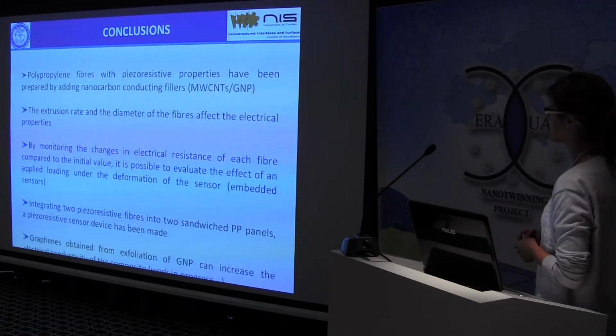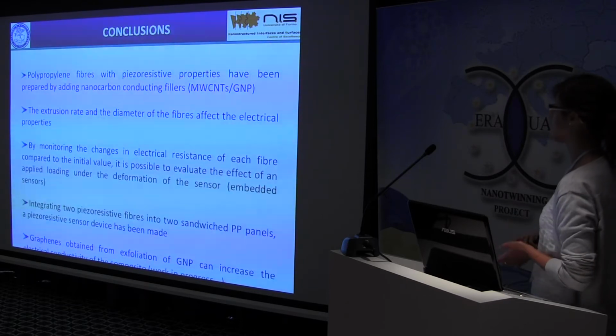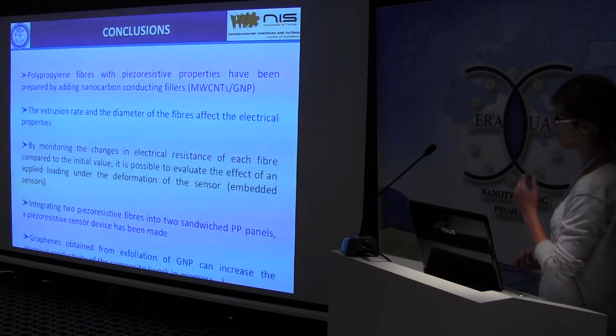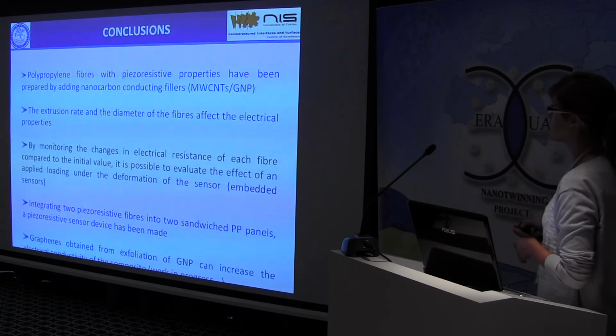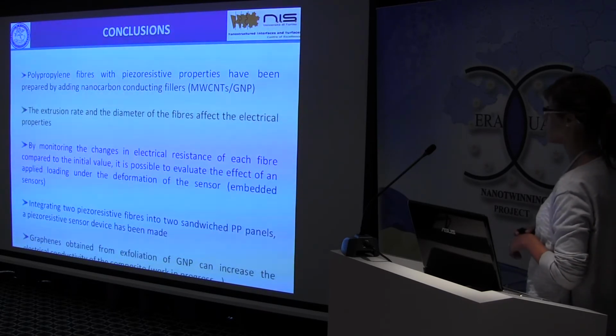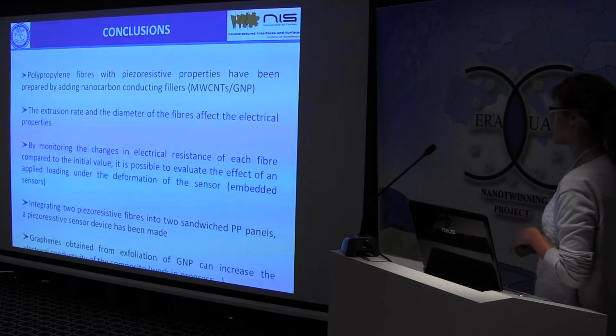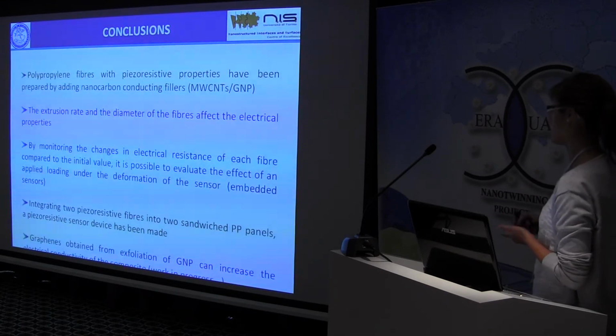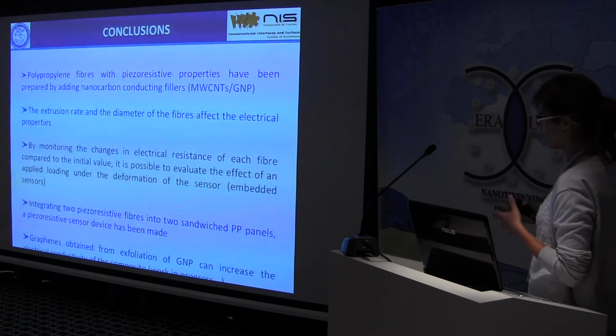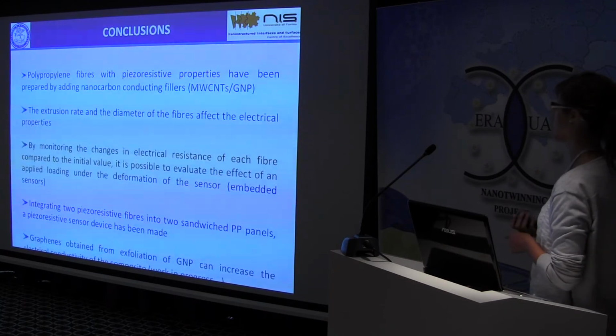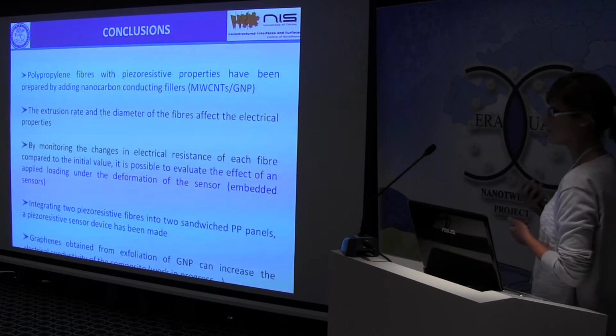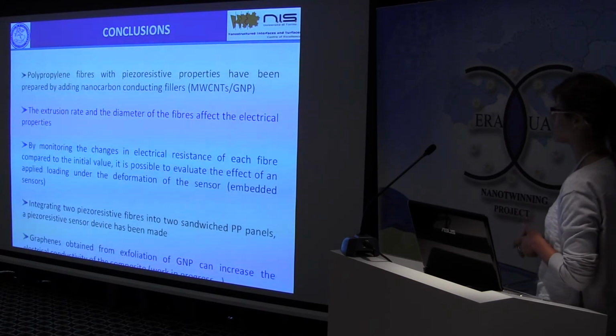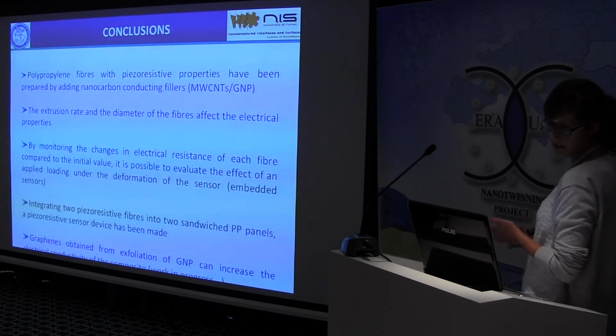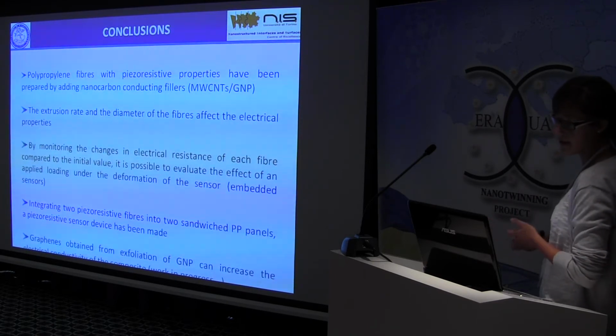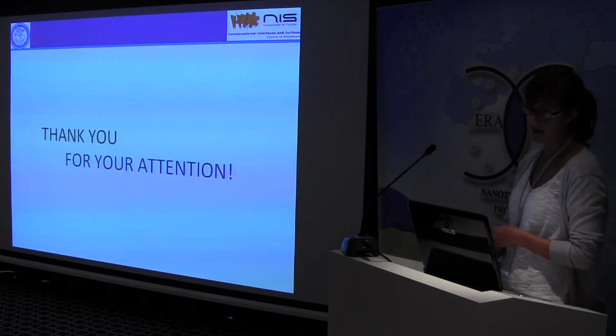Polypropylene fibers with piezoresistive properties have been prepared by adding nanocarbon conducting fillers, multi-walled carbon nanotubes or graphite nanoplatelets. The extrusion rate and the diameter of the fibers affect the electrical properties of the composite, and by monitoring the changes in electrical resistance of each fiber embedded in the panel, compared to an initial value, it is possible to evaluate the effect of an applied loading under the deformation of the sensor. By integrating two piezoresistive fibers into two sandwiched polypropylene panels, a piezoresistive sensor device has been made, and graphene obtained from exfoliation of graphite nanoplatelets can increase the electrical conductivity of the composite. Thank you for your attention.